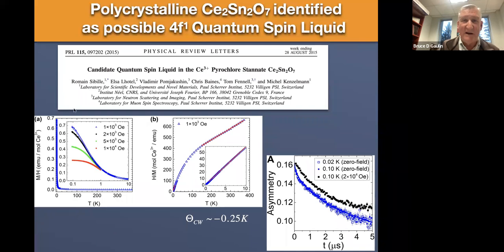Okay, at any rate, the main results of their paper are shown here. They're basically doing low temperature magnetic susceptibility and μSR measurements, and essentially all of these are consistent with no freezing and no long range order, down to dilution fridge temperature, so below, of order 20 millikelvin or so.